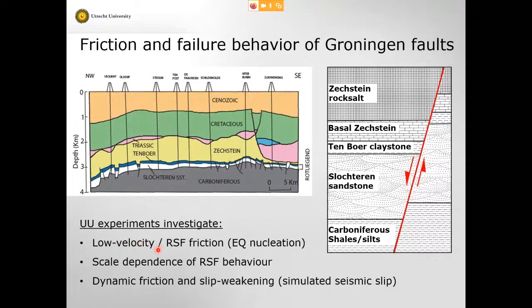We did low velocity experiments, a typical rate and state friction, classical sort of earthquake mechanics type of approach, to try to understand the nucleation stage of earthquakes, the slow initial growth of a rupture which might ultimately become unstable. We looked at the scale dependence, and we also looked at, okay, once a rupture has grown, once big enough, of course, you get dynamic failure and very rapidly accelerating behavior, dynamic friction, and usually you'd expect some very strong weakening. We also investigated that.